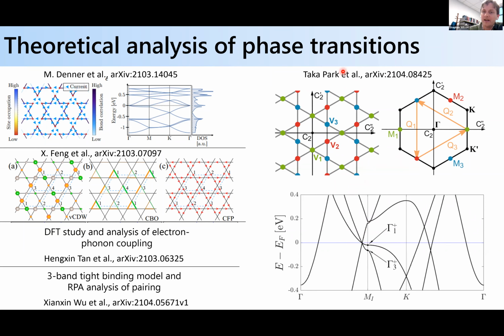There's also some very nice work looking at the different possibilities of having a real charge density wave state versus an imaginary charge density wave state that can break time reversal symmetry. I think in their analysis the leading instability is the real charge density wave order, but an imaginary component could potentially be activated, turned on via the application of a magnetic field.